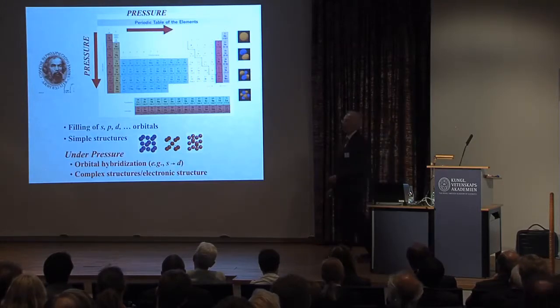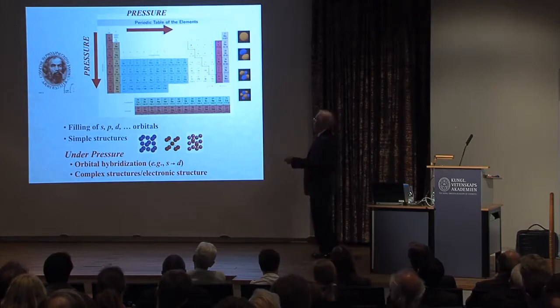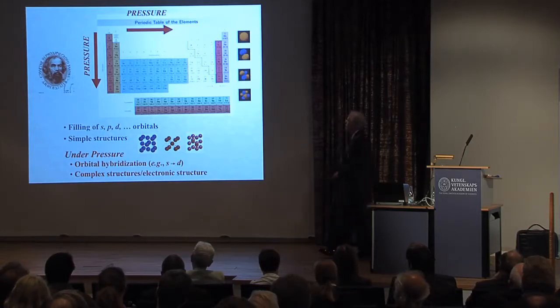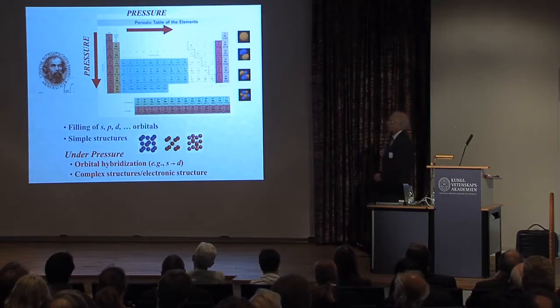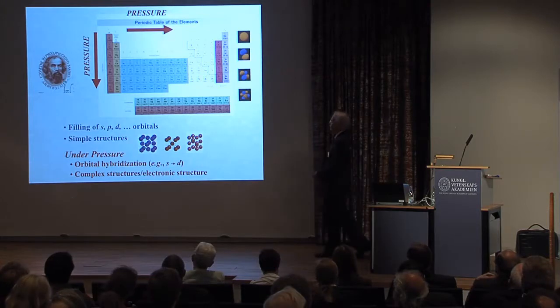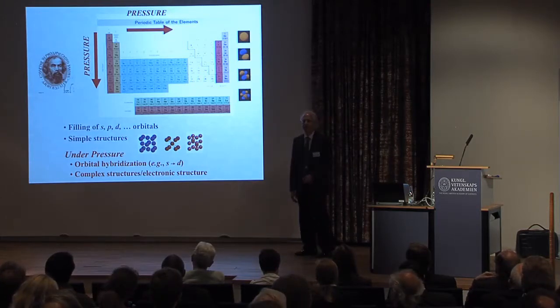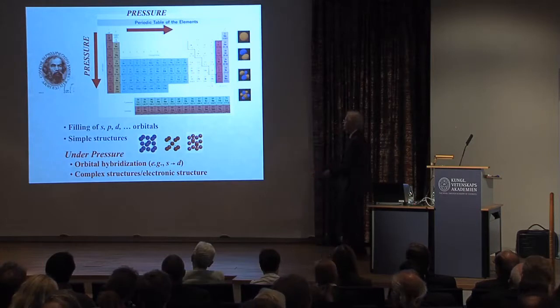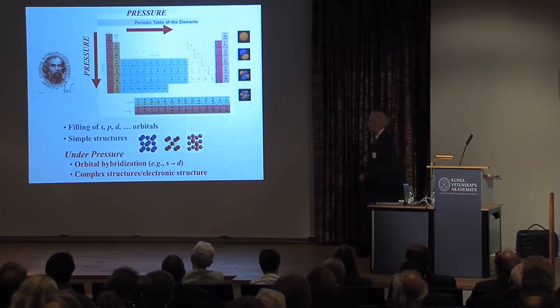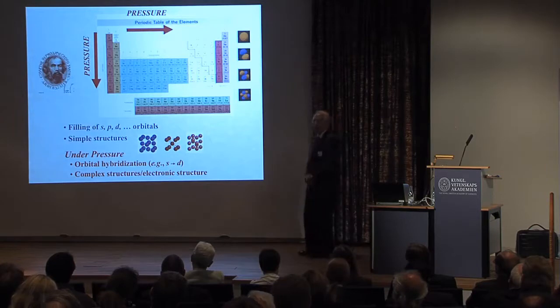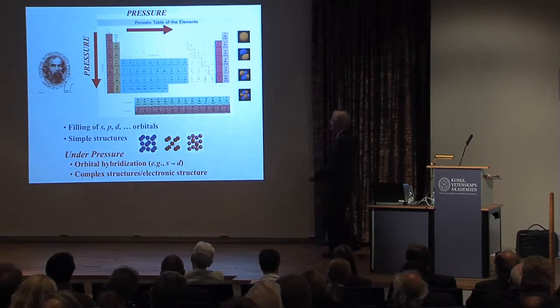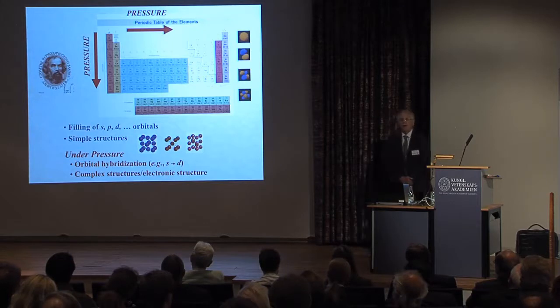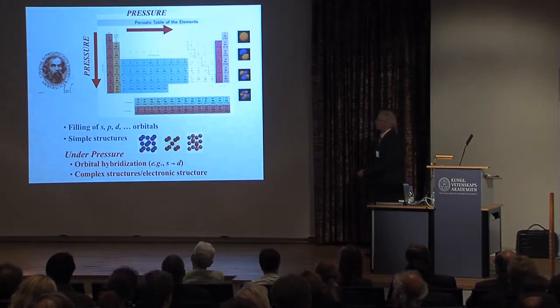What we find under pressure, and these are just rules of thumb, is that with increasing pressure, elements tend to start looking like elements below them in a particular column, and also elements start behaving like those to the right here as a function of pressure. And this is due to something called orbital hybridization, the mixing of these orbitals in a so-called S to D transition, for example. This was actually first pointed out by Enrico Fermi. And this gives rise to rather complex structures and a complicated electronic structure that I'll show you.